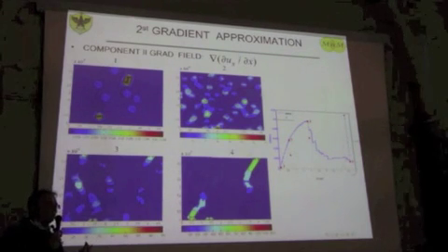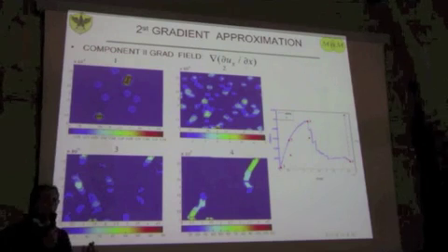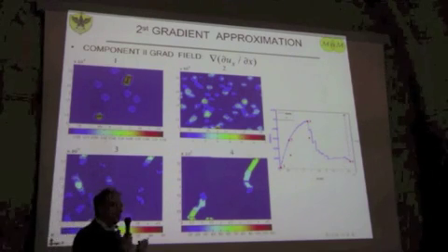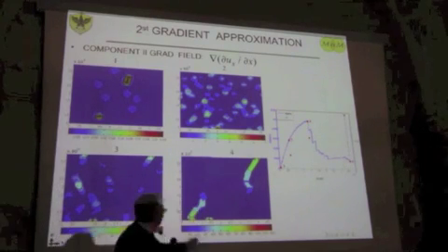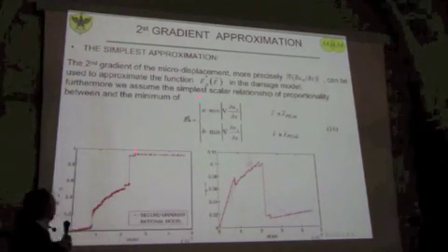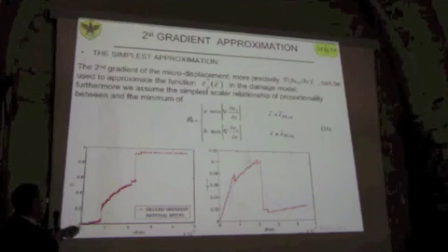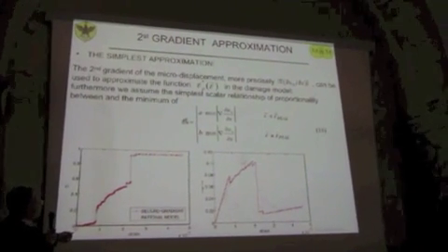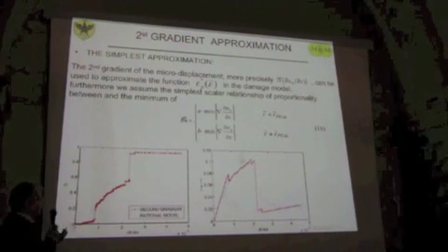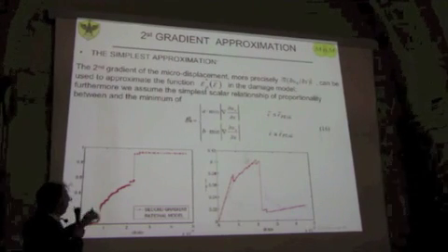And the key idea in this is, can the second gradient of the displacement convey the information about the stress fluctuation, so the critical strain of the grain boundary, the inner strength of the microstructure? If I take this field, the answer is actually promising, because if I make this assumption, this is the problem here. So the critical strain in my model is approximated as proportional, with a constant, with the minimum of the modulus of the field, of a component of the second gradient field.